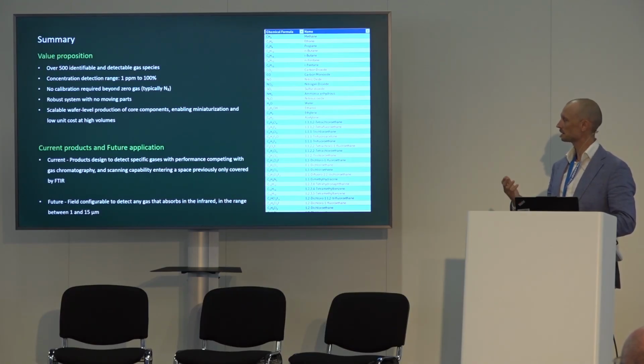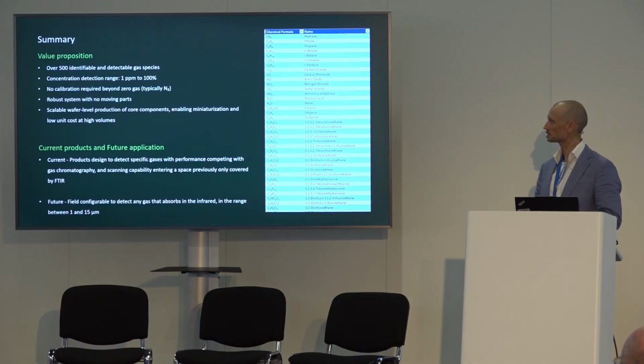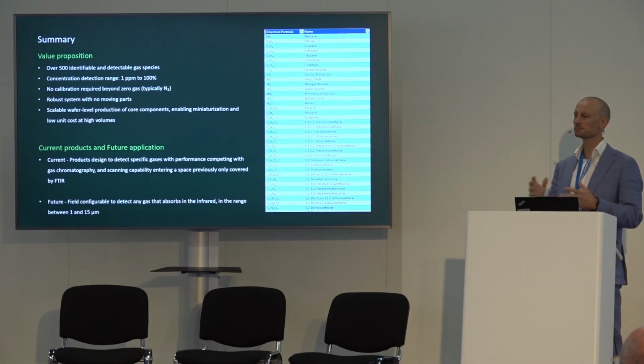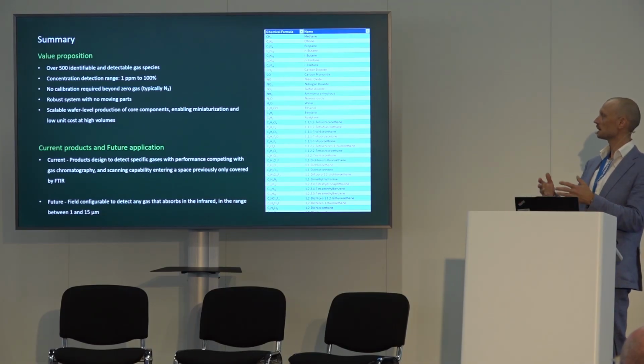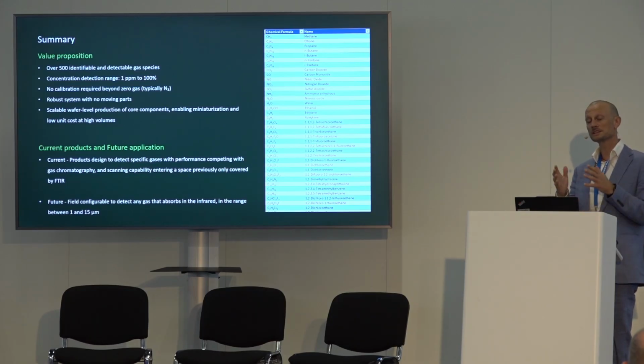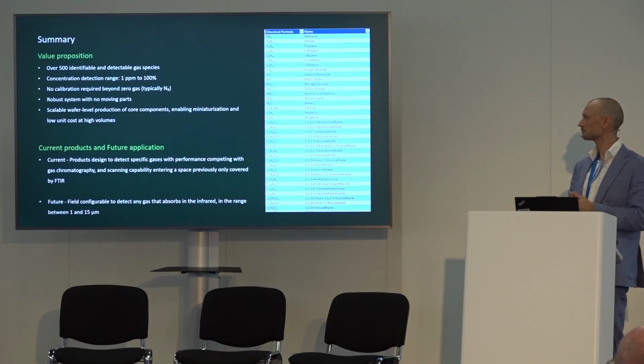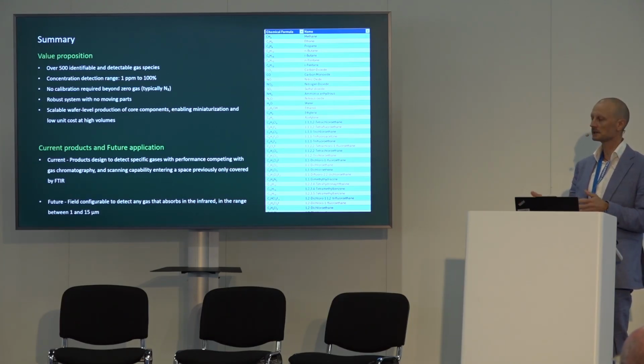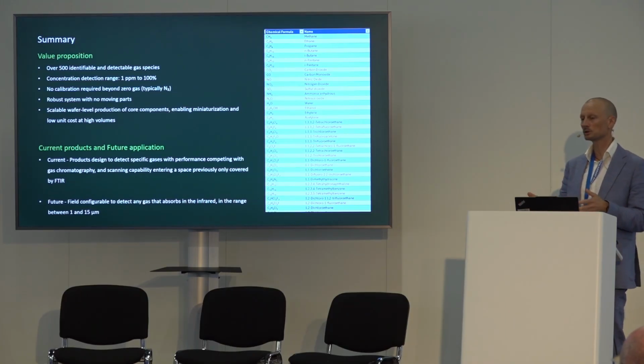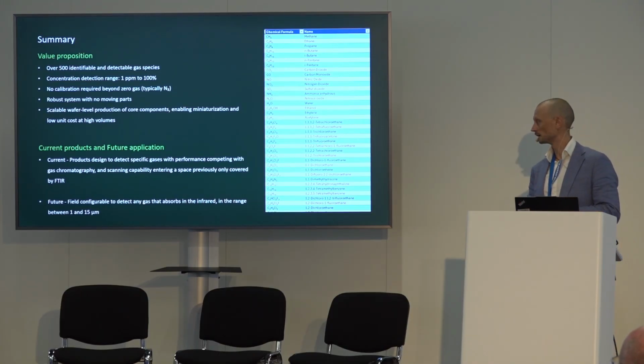It's a robust system as a result of no moving parts. And since we have a scalable wafer level production of our core component, that in the end enables miniaturization, of course. But for high volumes, we expect to be able to compete at a good price. So for current products, what this boils down to is that we can design systems and make products that detect specific gases that compete with gas chromatography. And we have the scanning capability that means that we're entering the space only covered by FTIR before.